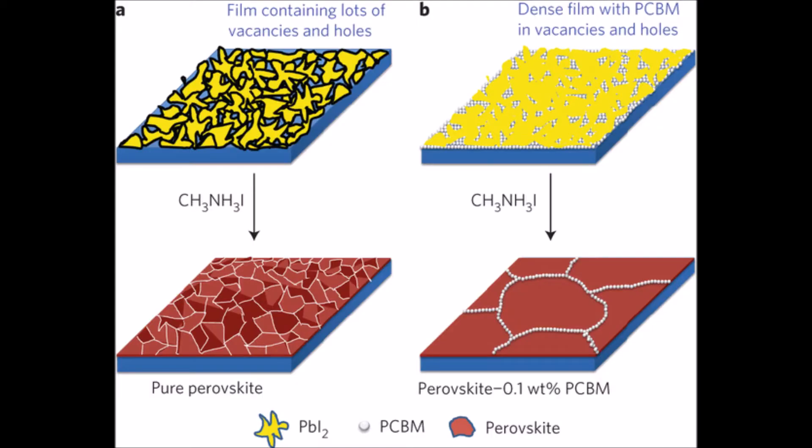For example, the processing of grain boundaries has a large impact on solar cell photovoltaic performance and radiative lifetime. Using processing methods to increase grain size leads to an increase in both properties.